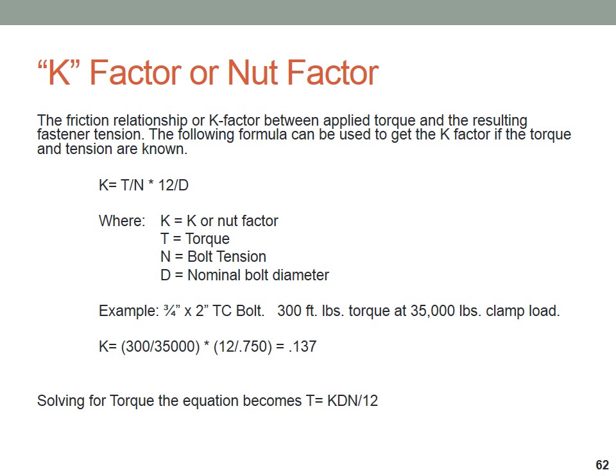We can come up with this value by basically going through a formula. If we know what the torque and the tension is, we can use this formula to get a K factor. And essentially this formula up here will give us that for any diameter of bolt. As an example, if we have a 3/4 by 2 inch bolt that has reached 35,000 pounds at 300 foot-pounds, that is a pretty efficient or effective lubricant. That would give us a K factor of 0.137. We can also, if we know a K factor, reverse that equation and come up with a torque out of that as well.